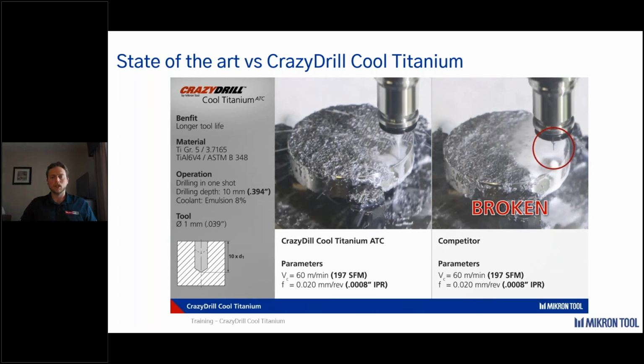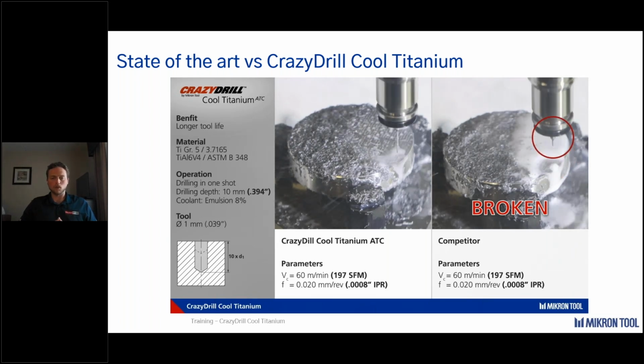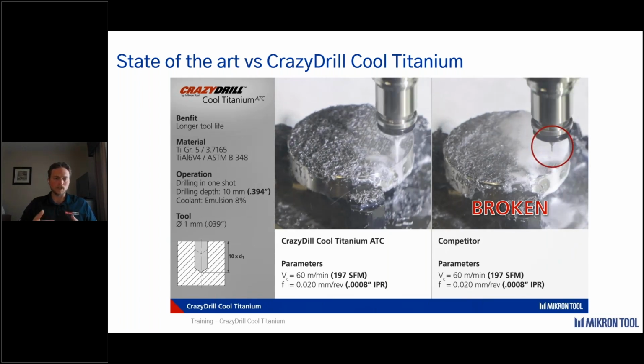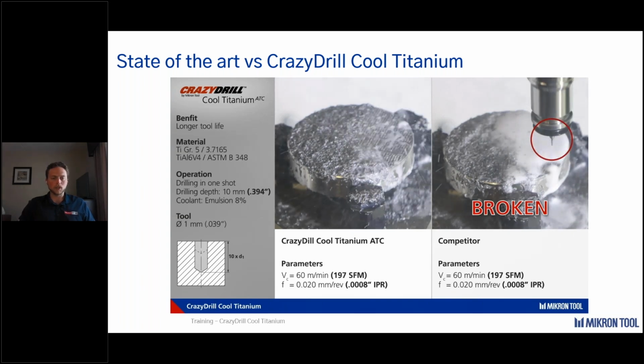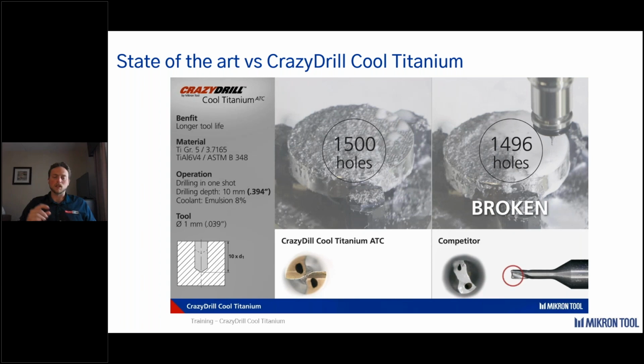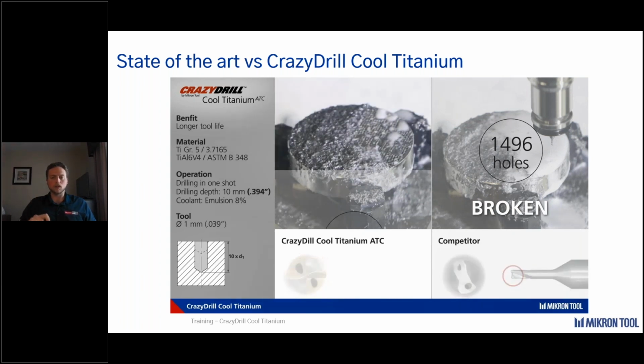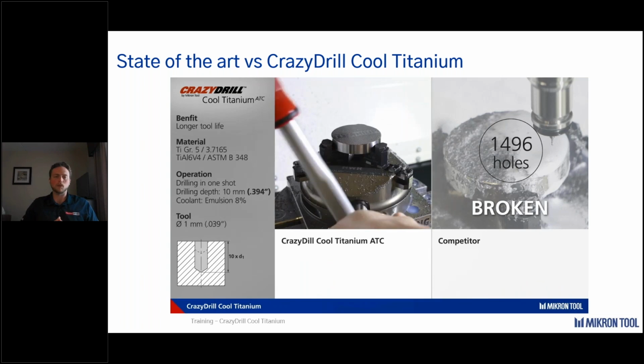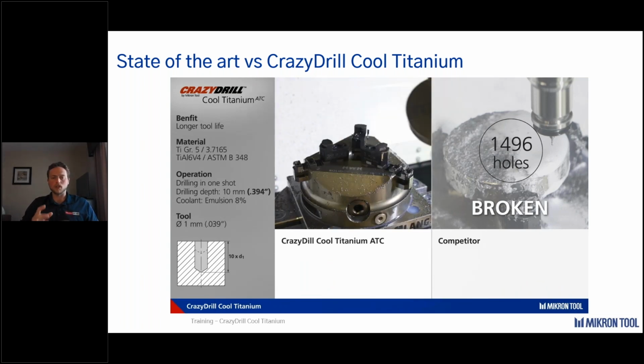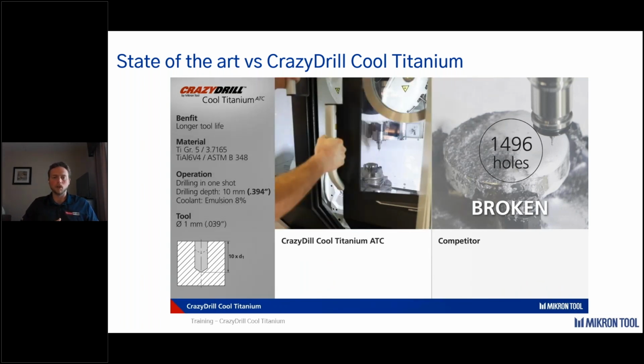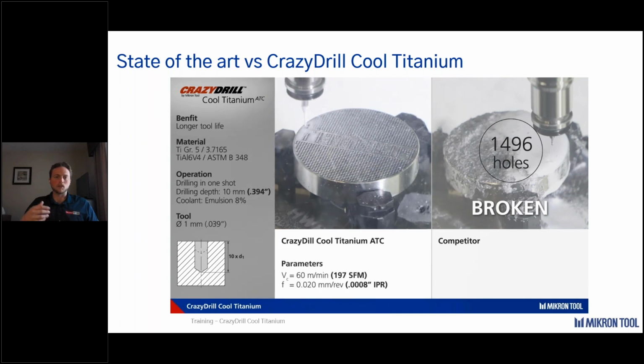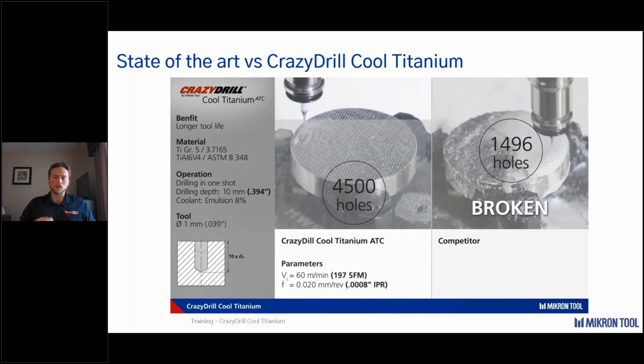So we took this tool and we wanted to have it meet the capabilities that we're seeing out of stainless steel. So in this example, we're running water soluble coolant. We're running it one shot, right? Now I say one shot as in we're not drilling anything from the 3 times D pilot to that 10 times D with peck. It's one shot from that standpoint. Each one of these holes, as you noticed at the beginning there, do actually have a pilot bore put in place first. That's able for that small diameter drill to have a starting point and find good position.